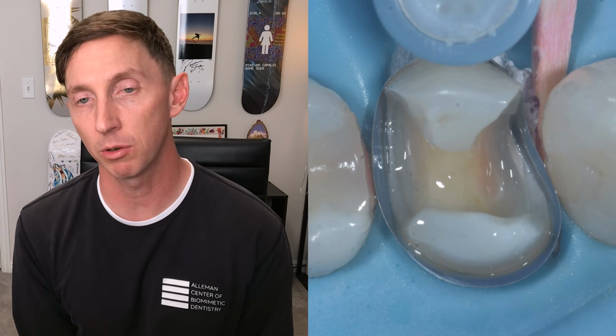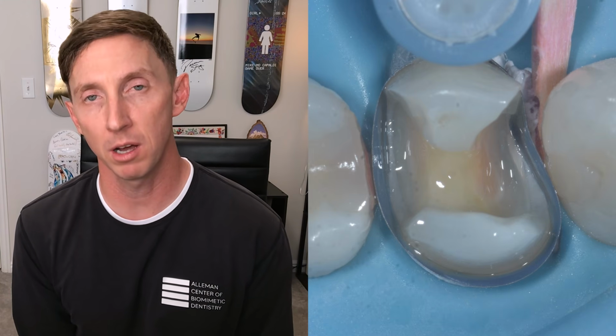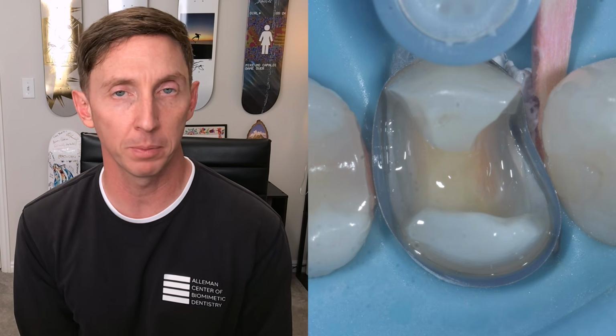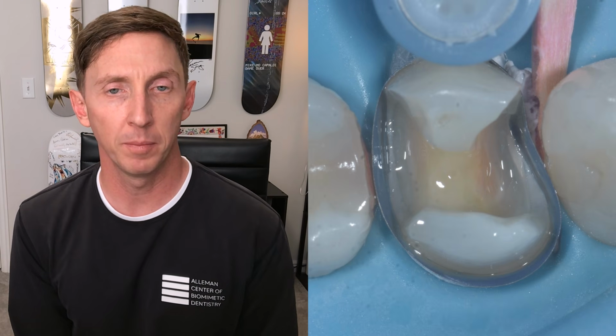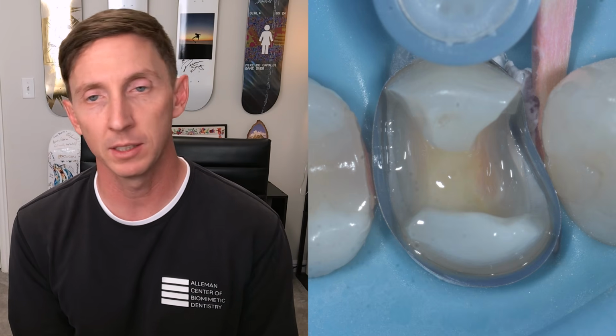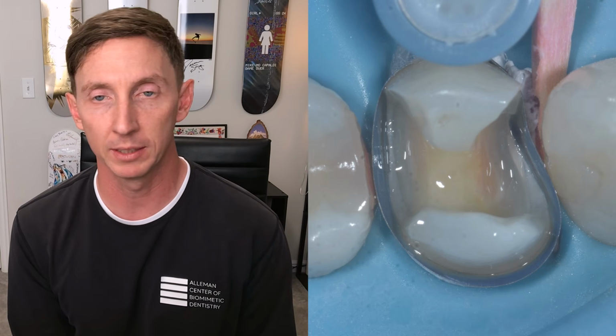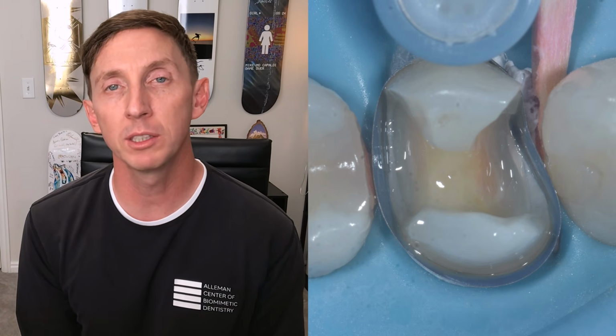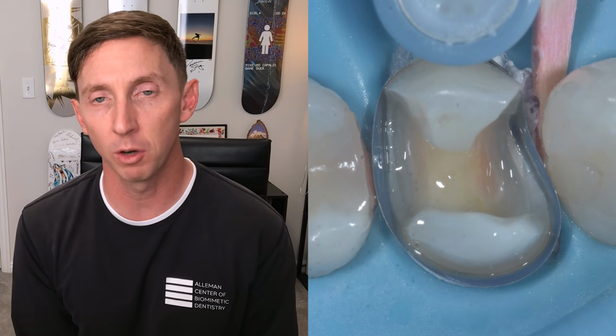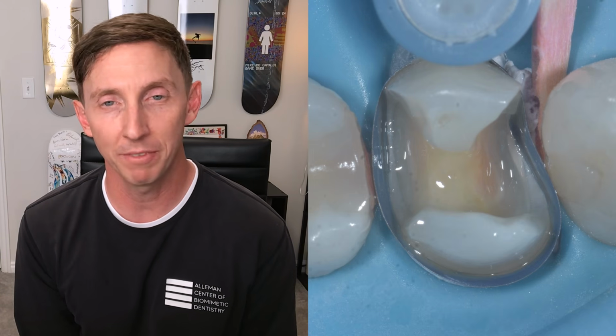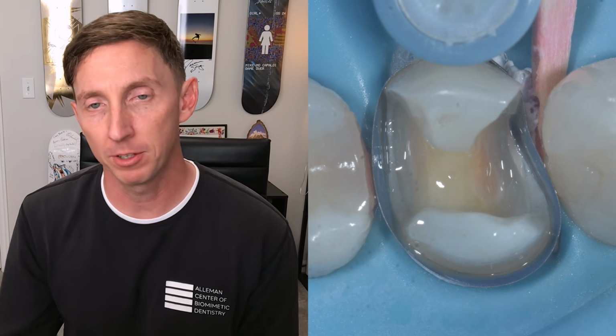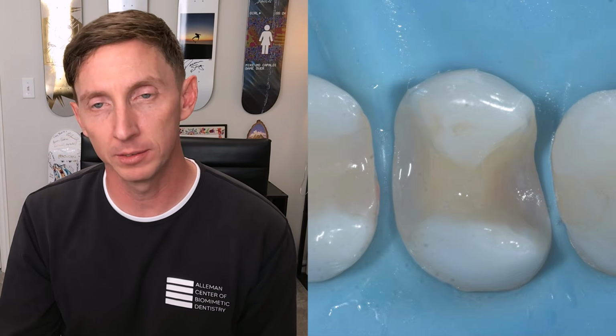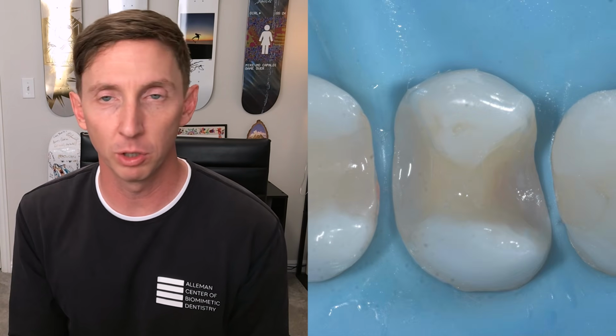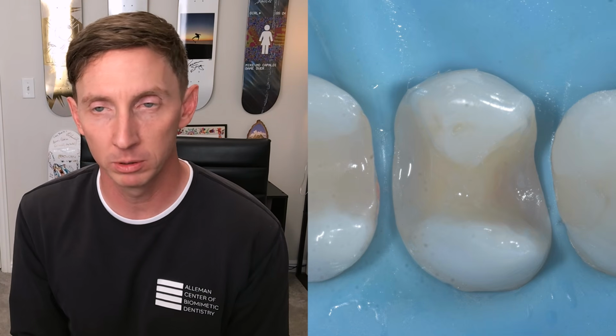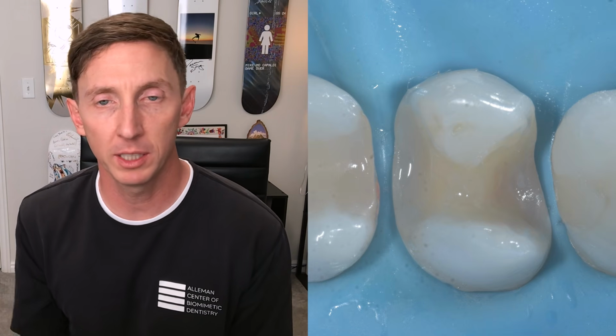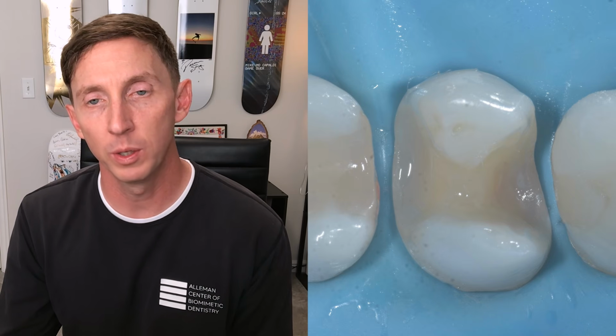The adhesive is now cured, and this is when the clock starts in terms of the decoupling process that we talk about when we train dentists in advanced adhesive and biomimetic techniques. In other words, in order for us to reach a bond strength that is greater than the cohesive strength of enamel, we have to wait a period of time. After we place the adhesive, cure it, then we do a resin coating. The resin coating will be a 0.5 millimeter of flowable. You will cure this. In this particular case, we restored with an inlay.